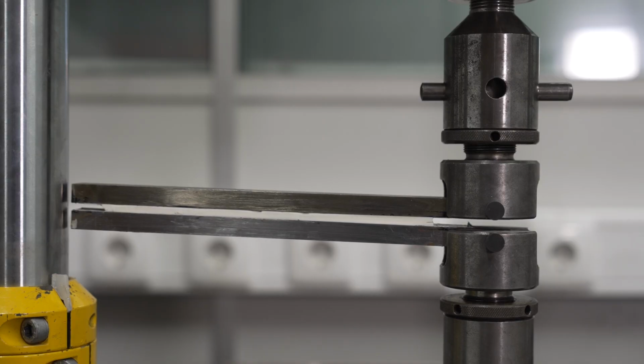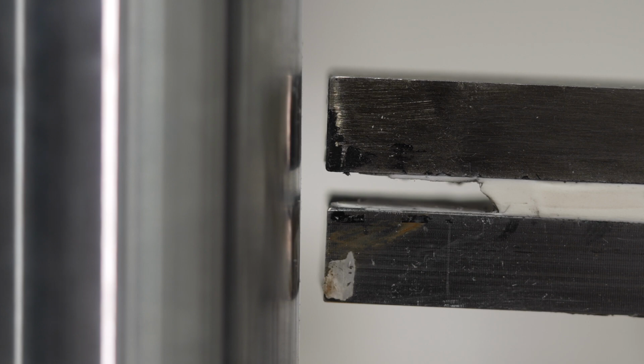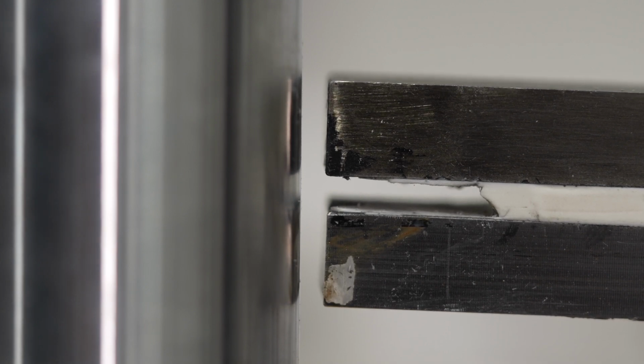When a joint is subjected to fluctuating stresses, like this one, it will experience a specific type of damage which is known as fatigue. So it's very important to characterize adhesive joints in terms of fatigue, specifically in terms of fatigue crack propagation. In this DCB test, we apply a cyclic loading to the joint, and we analyze the rate of crack propagation. The crack propagates from a small size to a big size, and we analyze the rate of crack growth under cyclic loading conditions.